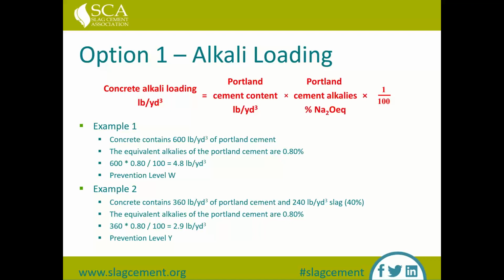For example 2, we'll take the same 600 pounds total cementitious material and the same 0.8% alkalis in our Portland cement, but this time use 40% slag replacement—360 pounds per cubic yard of Portland cement and 240 pounds per cubic yard of slag. The calculation is 360 times 0.8 divided by 100, equals 2.9 pounds per cubic yard. Since 2.9 is less than 3, that puts us at prevention level Y, a very high prevention level—a very strong mitigation level, being under 3 pounds per cubic yard of alkalis. One thing to note is that we are not using the alkali content of the slag cement itself, as we mentioned earlier, because the alkalis are actually consumed by the slag hydration.